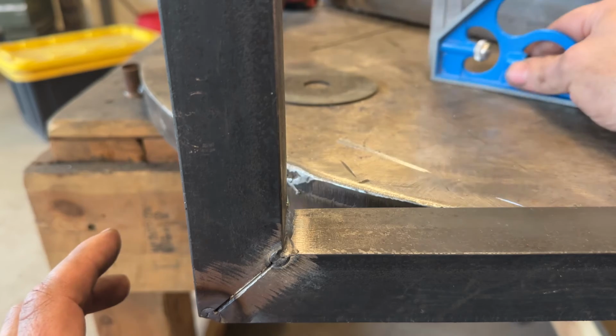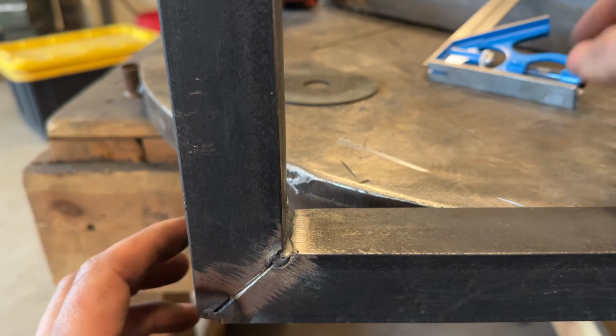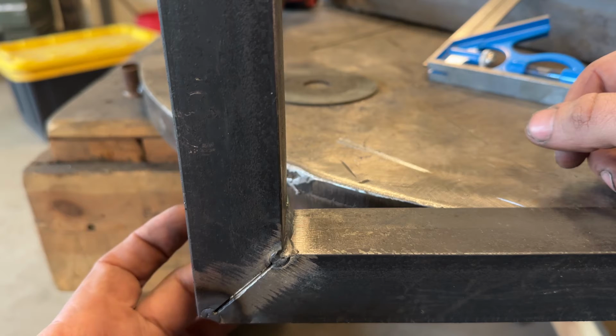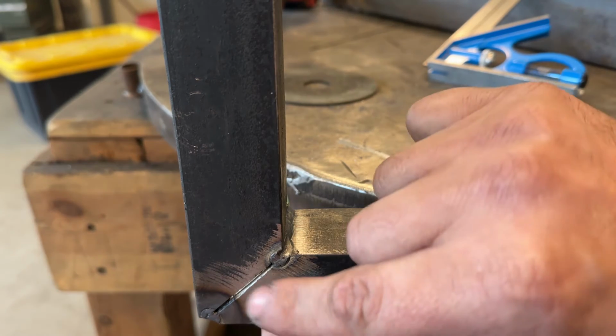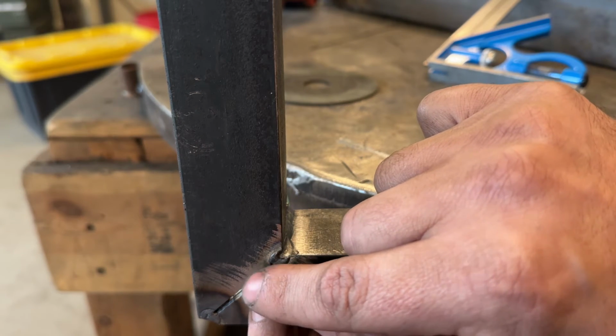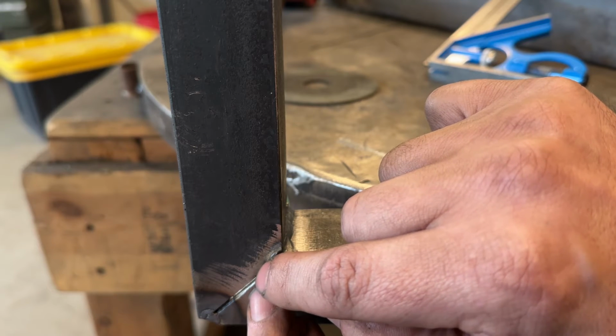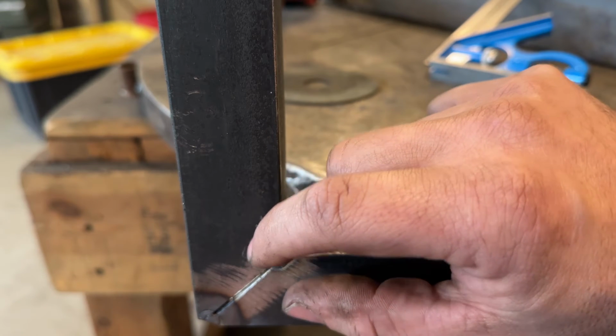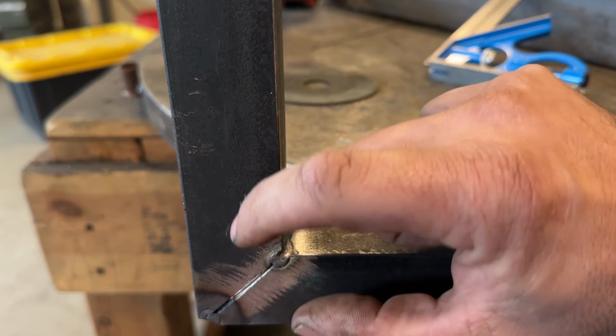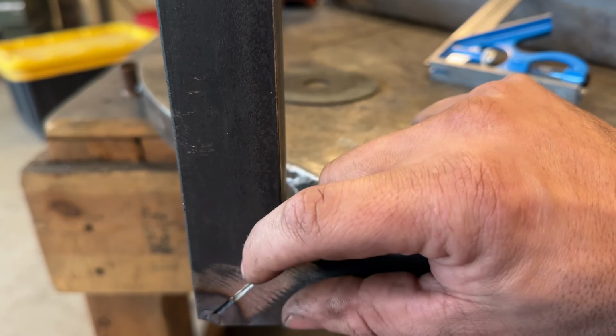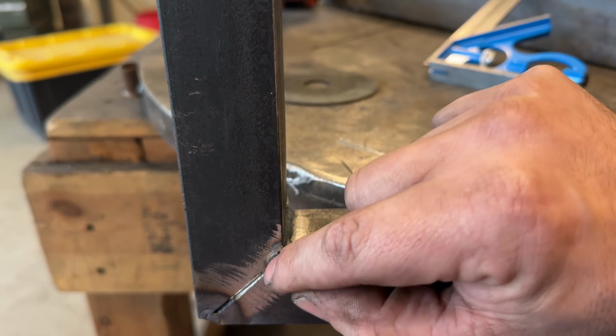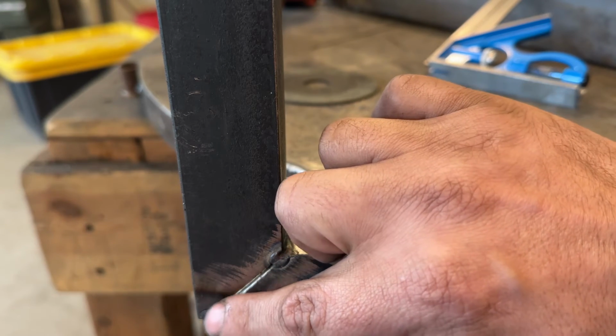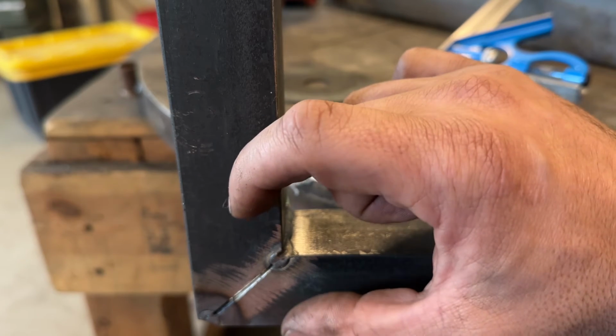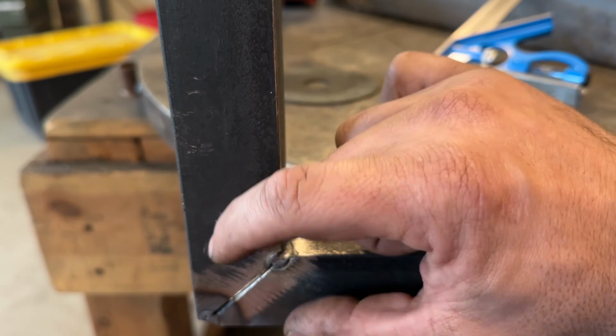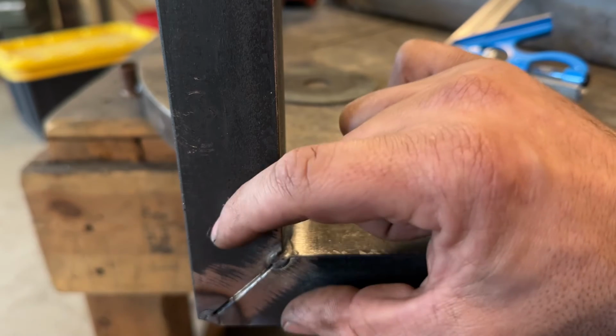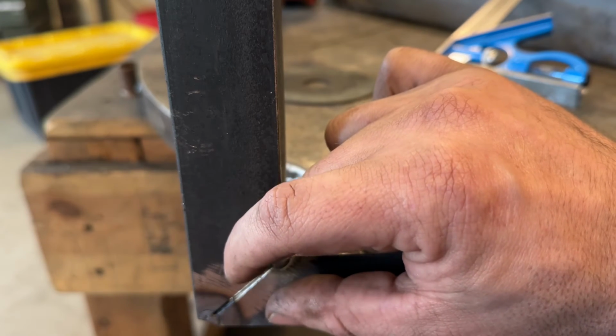So my thought is, we're close enough to the finish line here. I'm going to actually weld the inside, and I'm going to do spot welds. And the reason is that when I weld it and it solidifies, cools down, it's going to become solid. And then as I do another spot weld, it's going to have a harder time pulling because there's solid metal there. When you do one continuous hot bead, what's going to end up happening, just like in auto body, is it's going to pull tremendously because you now have that whole length of weld that's shrinking at the same time.